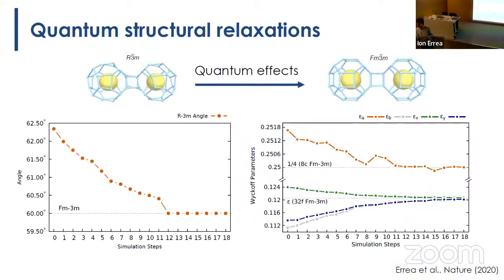So what we did was ask: is this related to quantum anharmonic effects? And indeed it is. We took this distorted structure as an example. We took several, but this is one example. It's a rhombohedral structure which has 4 different independent Wyckoff parameters. We started with this structure and did a relaxation, also variable cell because we are changing the rhombohedral angle. As we evolve in the minimization, this angle goes to 60 degrees, which is what you have in an FCC description of the lattice. You can describe an FCC as a rhombohedral lattice with 60 degrees in the primitive unit cell. And the Wyckoff positions evolve into something that precisely matches the FCC Wyckoff positions. So this structure is changing into this structure thanks to quantum anharmonic effects.